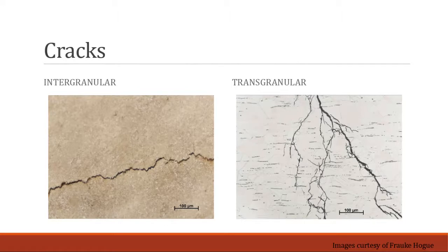So if I were to zoom in a little bit on the one that's transgranular, you can see that the cracks are cutting across the grains. They're not following grain boundaries. This one over here looks more jagged. The prior austenitic grain boundaries might be a little bit on the small side, but if you picture, if this was a grain, something along those lines, and then of course the grain on the top, this is typical in quench and tempered materials that crack due to embrittlement conditions.